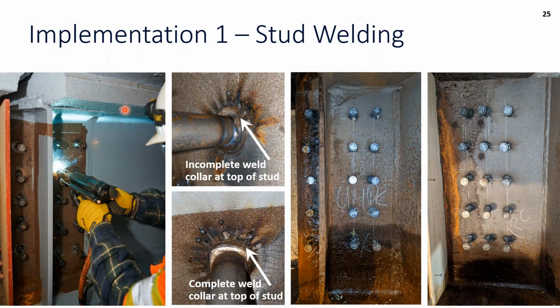So the first thing that's really critical that I want to know when we're looking at these weld collars is that we count on a complete collar around the stud. And we did have several issues when it came to having this kind of gap around in the top. And that's just something to make sure that the inspector is on board with, that they're looking out for. And we handled that by either adding additional studs, so we weren't counting on the capacity of this stud with the incomplete collar around it, or some of them went back and they were repaired with just some stick welding. So this is really important, and this is why we have to have that thorough cleaning of the place right underneath the studs. It's a really critical component.